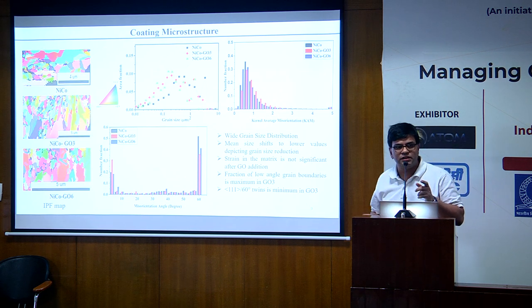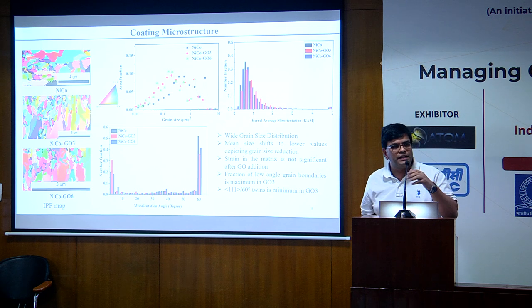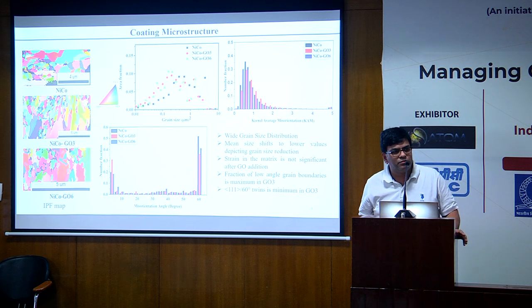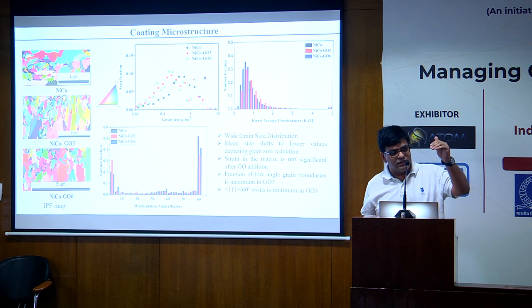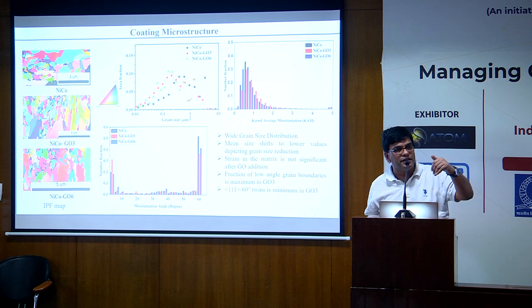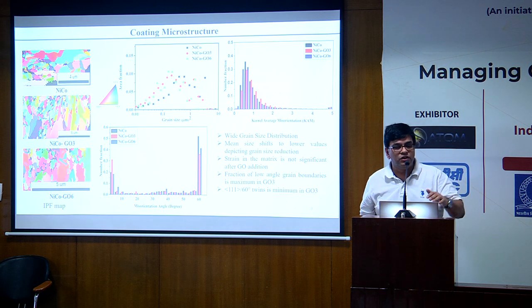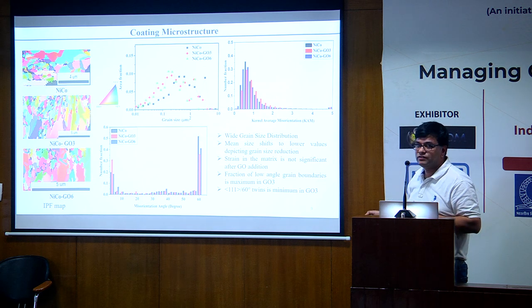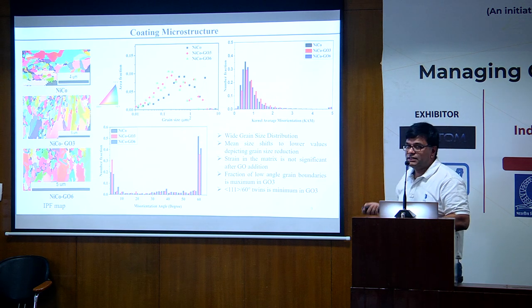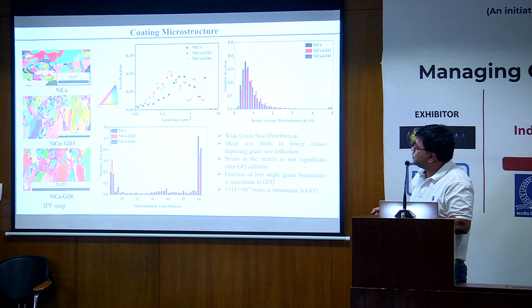And in this GO3, we get the maximum number of those boundaries which are lower energy boundaries. So if we add graphene oxide, that provides a certain kind of impermeability to the coating, because the chlorine and the corrosive media cannot penetrate very easily through the graphene oxide. It also changes the texture of the coating. And why this happens? The question is why? So we do some kind of a TEM.